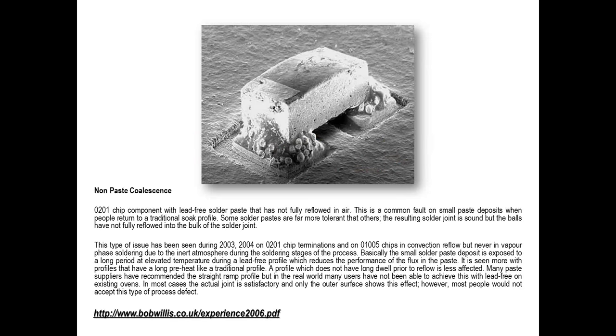So basically, what we're talking about is the solder paste material during the reflow cycle was actually being exhausted. So the volatiles plus the fluxing agents and gelling material were being exhausted, and we're left with the solder. And there wasn't sufficient material to protect the surface. Now, if you were running vapor phase or you're running in nitrogen, you wouldn't see this as a problem. But if you're running in air or very low nitrogen, you would still see this as an issue.